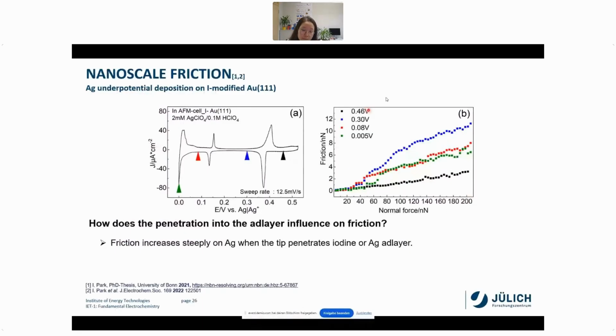This is the friction data as a function of normal load. The color code matches the cyclic voltammetry, and it shows there is a steep increase. For the blue case, there are two increases, and they match the penetration into the iodine layer or silver layer. But for the gold case, there is no steep increase. So probably it means that there are some interaction changes. We have to study more what kind of interaction actually happened there. But it indicates that friction measurement can show surface reactions, or if something is happening at the surface, then we can immediately see it by friction measurement. Therefore, friction measurement is very important. I want to say that. And now Florian will show you more about friction on energy materials.